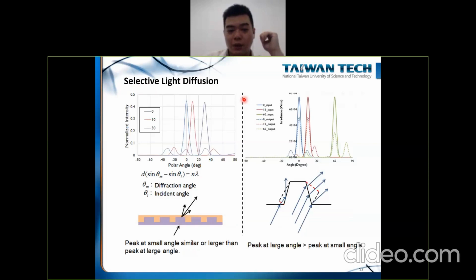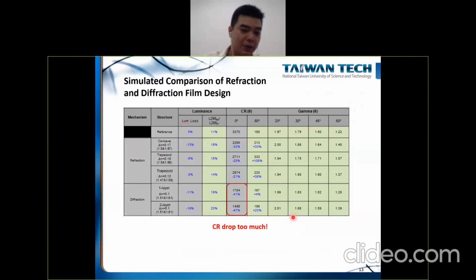So which way is better? Actually for the design, we have some targets. For example, don't sacrifice too much contrast ratio in the normal direction. We don't want too much transmittance loss in the normal direction. So we simply simulate this type of structure, and we have a commercial TV with no diffraction film as the reference.